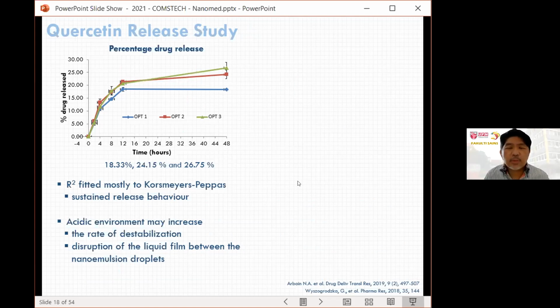But in comparison with quercetin alone, which is less than 10%, we've been able to release the drug at almost 25% for this formulation 3, and it basically fitted the Korsmeyer-Peppas model, and it showed sustained release behavior, particularly in acidic environment. So it increased the rate of destabilization and then disrupted the liquid film between the nanoemulsion droplets.